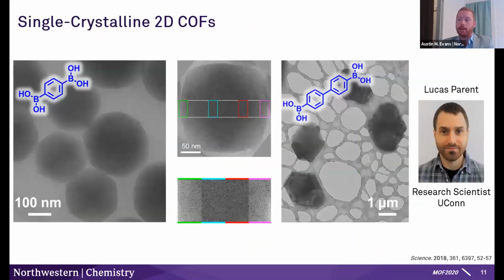But I think the most compelling evidence here is the TEM of these grown particles. So after growth, we can still look at the TEM, and you'll see these particles are quite a bit larger than the ones we started with. And so the growth that we hope to encourage seems to have happened. And really exciting, you can look at the lattice fringes of a single particle, and they actually extend from one side all the way to the other. And that gives very good evidence that the particles started as single crystals and then grew as single crystals as well.